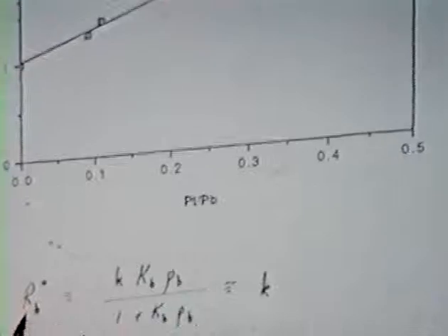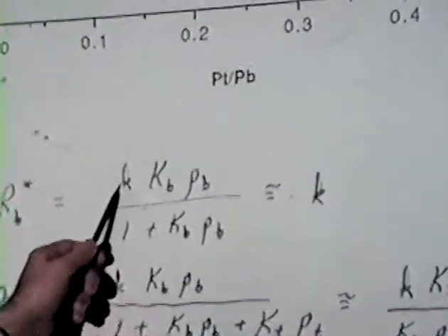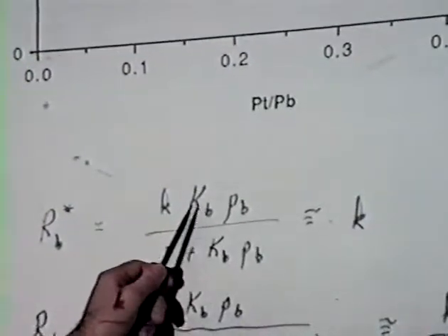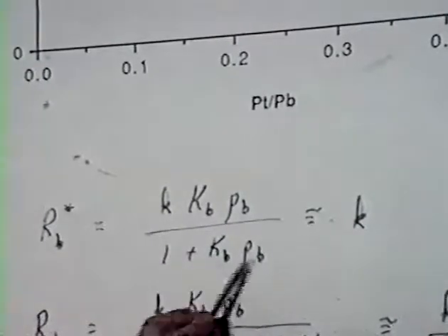Okay. Now what do we do? Well, we measure the adsorption equilibrium constant, but we want to do it under reaction conditions, and so we measure it kinetically. The rate of benzene hydrogenation in a Langmuir form is a rate constant times the Langmuir adsorption expression, which is just the equilibrium adsorption constant for benzene times its partial pressure over 1 plus that.